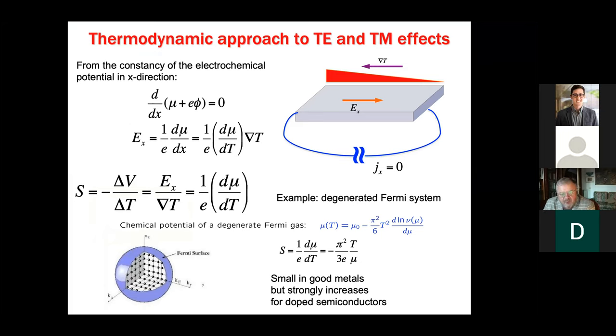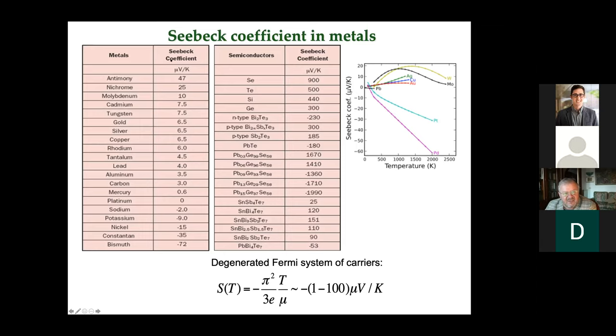It is possible to show that the Seebeck coefficient, if we do not take into account the scattering processes, so in the thermodynamic approach, is proportional to dμ/dT, where μ is the chemical potential of our sample. For a metal, the chemical potential is the Fermi energy, the chemical potential at zero temperature, minus T squared divided by μ. So you see immediately, unfortunately, this smallness in the derivative dμ/dT contains temperature divided by μ: temperature 300 Kelvin, μ several electron volts. So you will already have a smallness of 10 to the minus 3. And indeed, metals have very small Seebeck coefficients, expressed in tens of microvolts. The maximum may be bismuth, which has 72